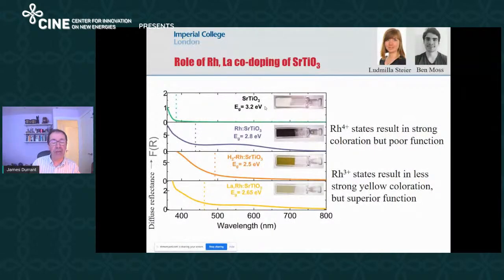Now what you can see is that the doping with the rhodium and the lanthanum changes the color of the strontium titanate. Strontium titanate's white. It's a wide bandgap semiconductor. It's not much use for absorbing photons. When you dope it with rhodium, it becomes very strongly pigmented. But this strongly pigmented strontium titanate is rather non-functional in terms of being able to split water. But if you reduce that rhodium, either with hydrogen or by co-doping with lanthanum, you end up with something which is still colored, not as strongly as with rhodium, but which is far more functional. So you lose coloration, but you gain function. And we wanted to understand why that was.